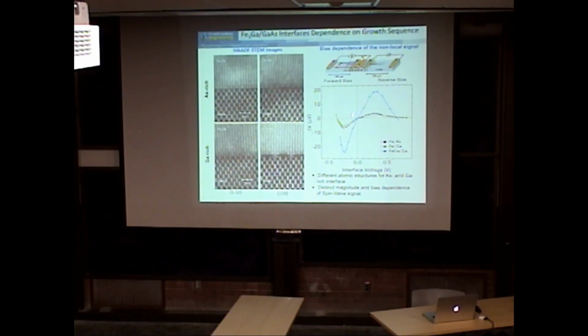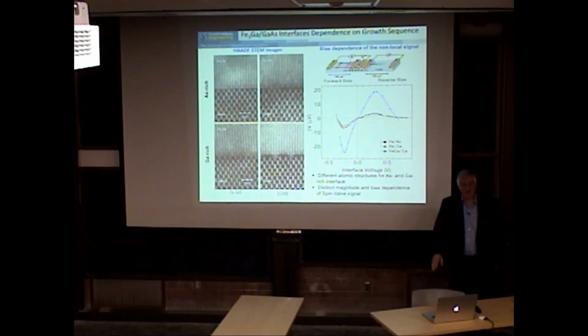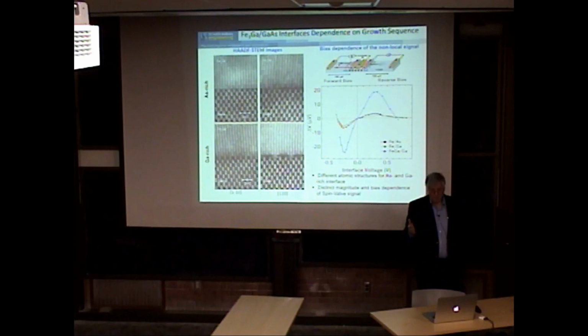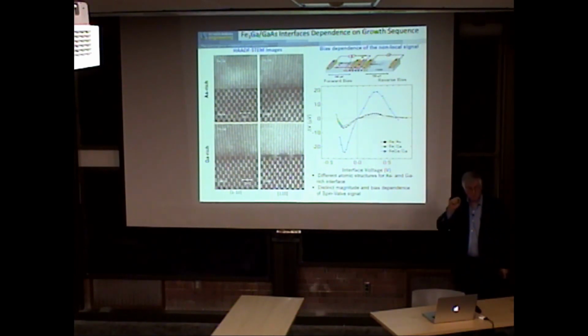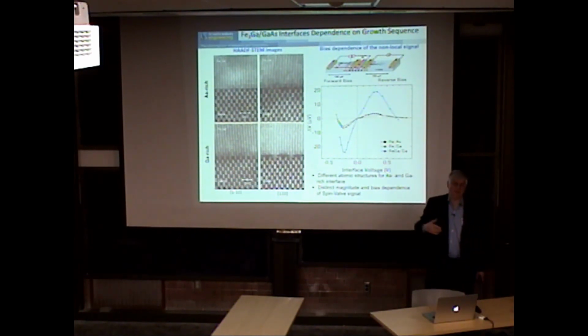So one of them is injection, the other extraction; forward bias, reverse bias is just changing the direction of the current through that contact. But you cannot foresee it. I mean, can you guess that this is what will happen? Well, it depends. I'm not a theorist, so I don't need to guess. No, I'm allowed to guess. But the theorist is supposed to tell me I'm right or wrong, right? Or predict? Okay. The only thing I can say is that iron 3 gallium is a ferromagnet. Gallium-rich iron gallium compounds tend to be magnetic. Iron arsenic tends to be antiferromagnetic. So my first reaction would be that if I have iron arsenic at the interface, I'm probably going to get less spin injection. But I didn't know that a priori. With hindsight, I can use it as a hand-waving argument.